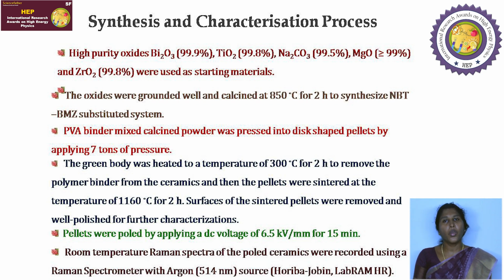and the well polished pellets are used for the characterization purpose. Before going for the structural and Raman spectroscopy as well as the electrical properties, the pellets were poled by applying a DC voltage of 6.5 kilovolt per mm for 15 minutes. The Raman spectroscopy is taken using an argon source of wavelength 514 nanometer.